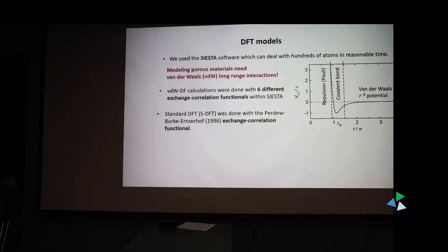But in the framework of DFT, van der Waals interactions are included in the famous exchange correlation functional. Okay? We're going to try six of them. And we will also do a standard DFT, meaning standard because not including van der Waals interactions, and we use the well-known PBE functional.